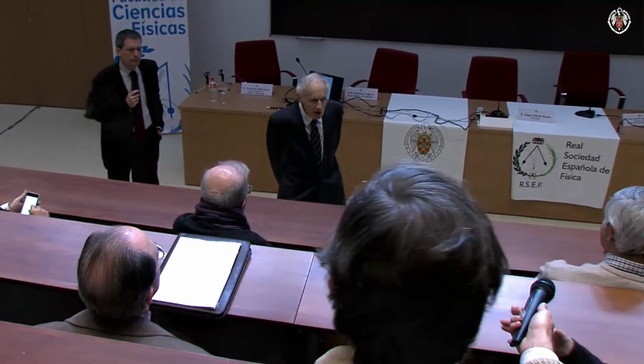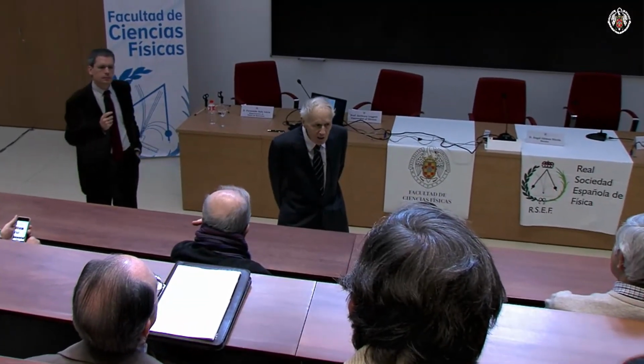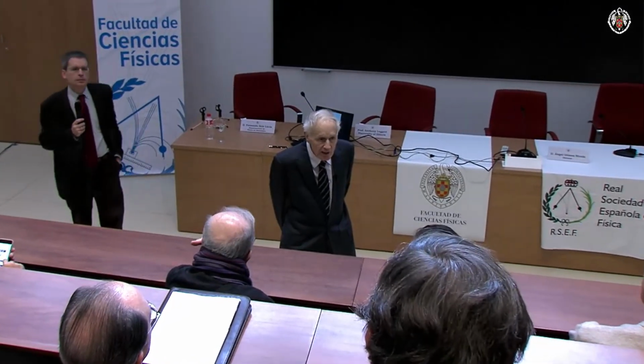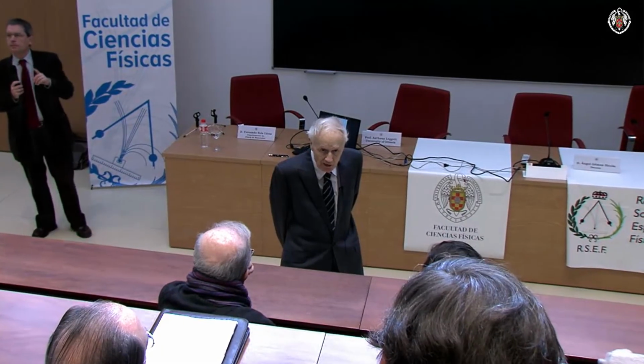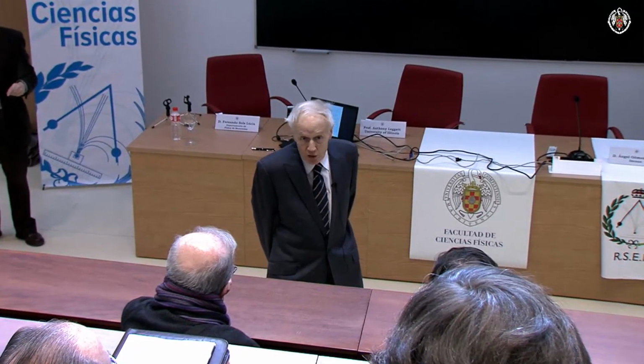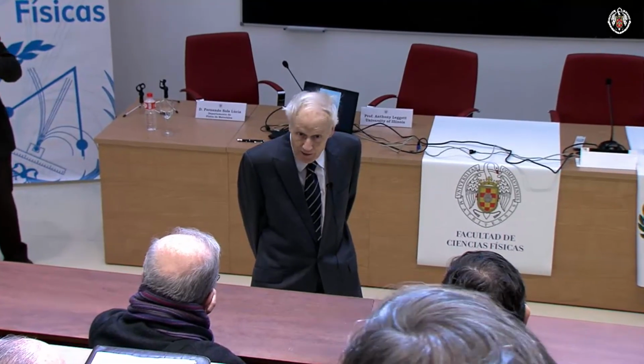So the question was about the class of iron selenide materials, which was, as you say, originally discovered in China to be a relatively high temperature superconductor, about a third of room temperature, perhaps a little less. And the question, how does that fit in? The answer is we don't know. One possibility is the lattice of the superconductor itself. But in this case, it turns out that you only get this effect when the iron selenide is laid across a substrate of, for example, strontium titanate, and it may actually be the ions of the strontium titanate lattice which are producing the polarization which is necessary. That's only one possibility. There are many others, and I think right now one has to say there's no general agreement about how that works.